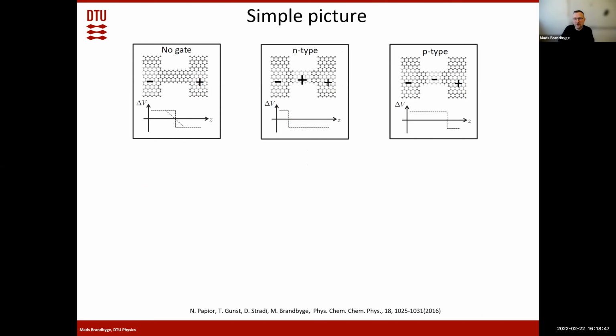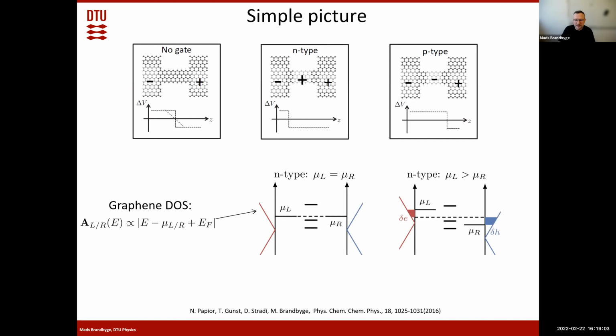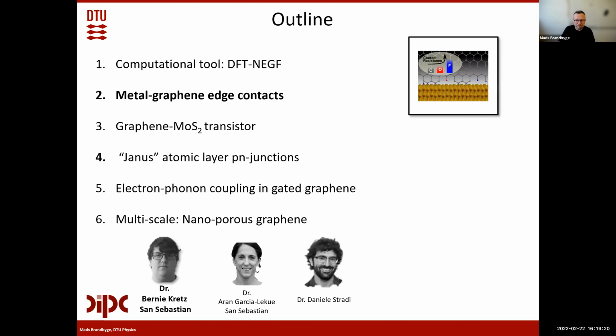And we can take, of course, the calculation apart and see what is the reason for this change in voltage drop. And that's basically the change in charge in the ribbon part here. It will change its charge once we apply the bias. And we can understand this change in charge by looking at basically the density of states in the electrodes. But this is just to show the way we operate. We do these calculations and then we analyze the results afterwards to understand more deeply what goes on.